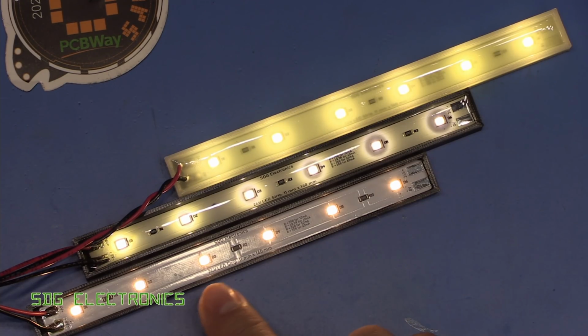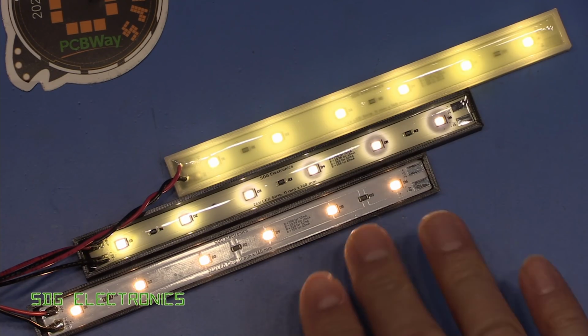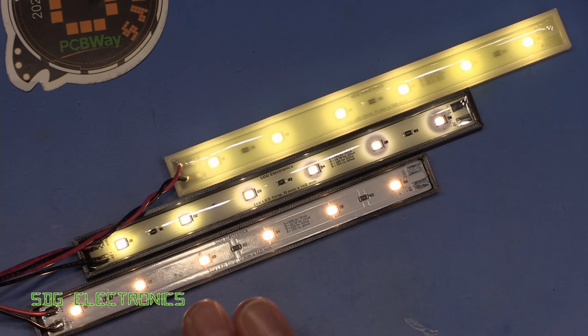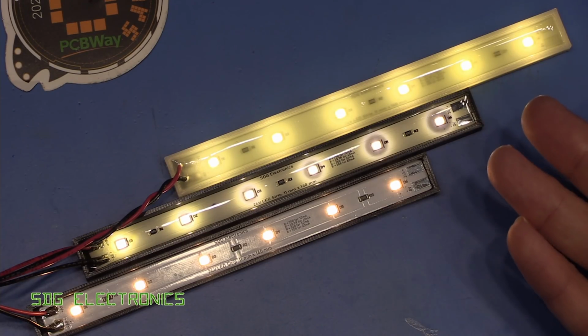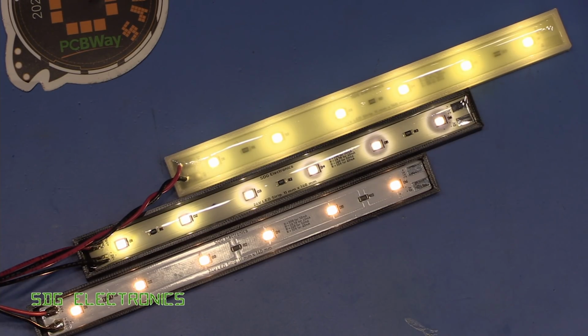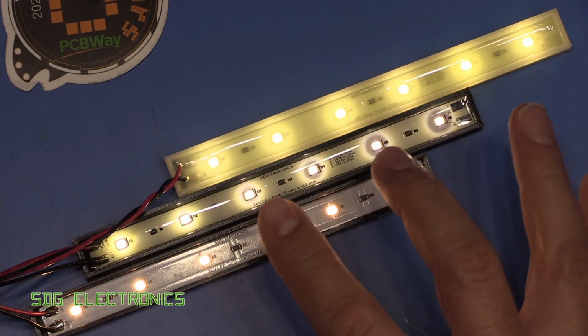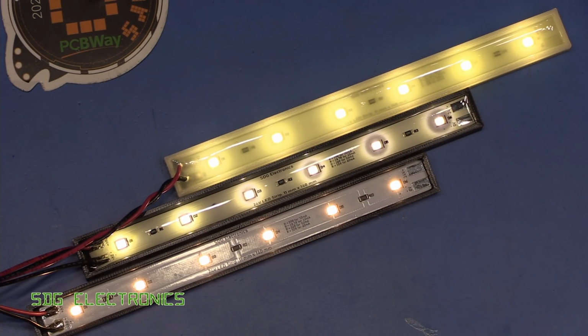Possibly what you might want to do is just coat the PCB up to the level of the top of the LED so that you don't actually cover the top of the LED, and that should maintain the waterproofing but it won't affect the colour temperature at all. And then secondly, if you are thinking about adding something like some glow-in-the-dark pigment, be aware that in order to operate, it is absorbing some light in the 450 nanometer region, and basically you're going to remove some of the blue light from these LEDs in order for that glow-in-the-dark pigment to work.